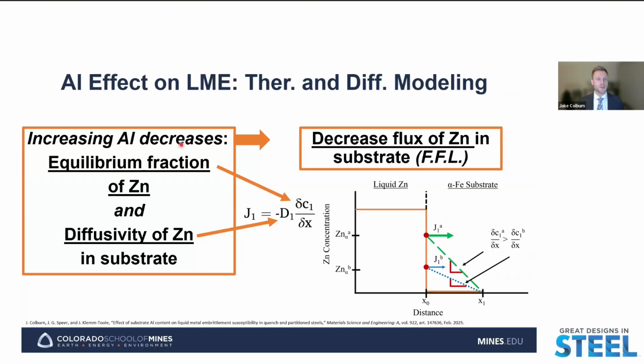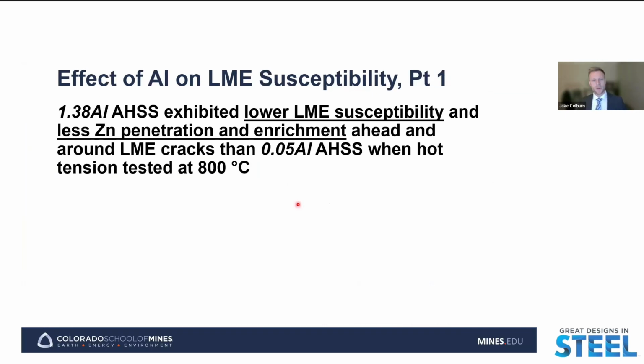So we see that increasing the aluminum concentration should potentially decrease the flux of zinc in the substrate by both of these factors here, by decreasing both the diffusivity of zinc and that concentration gradient of zinc into the substrate. And so if we take some of those points together here with a quick sub-summary, we